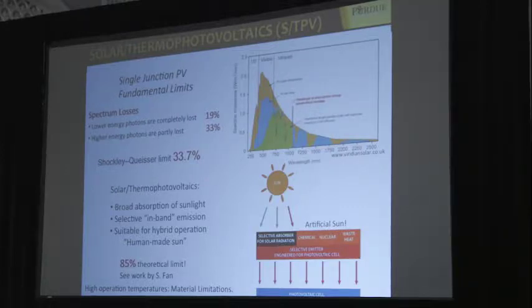But on the other hand, it's well known, at least theoretically, that if you would do it in a different way, if you basically use heat and let this object, which is heated up to high temperature, let's say 1500 Celsius, radiate the Planck radiation, but control this radiation. And with plasmonics, you could control it to a great degree. So basically, you could make it emit light only at the wavelength which matches exactly the band gap of your photovoltaic cell. That could dramatically increase the efficiency.